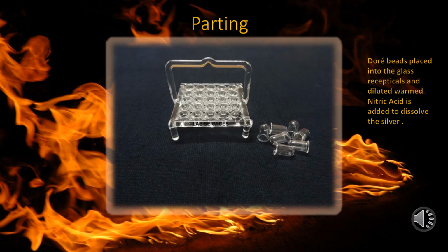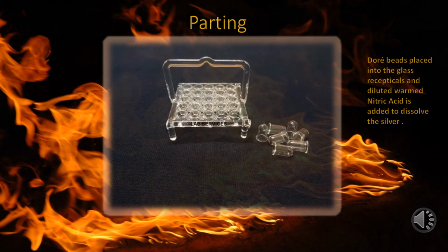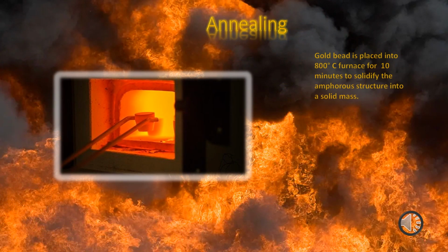The parting process, if completed efficiently, will produce a gold bead that can be up to 3 to 4 nines fine. There is, however, one more step in the process, and that is annealing. Once the silver has been parted from the bead, the result leaves the bead as amorphous in structure. This means that the bead will be filled with minute holes throughout from where the silver has been dissolved. The gold bead will not be a single piece of precious and noble metal. Annealing results in a solid piece of metal.